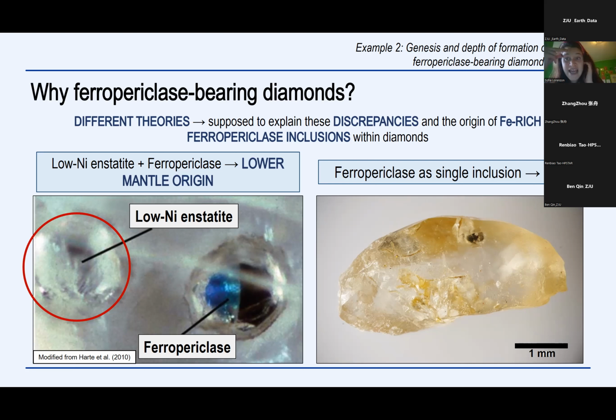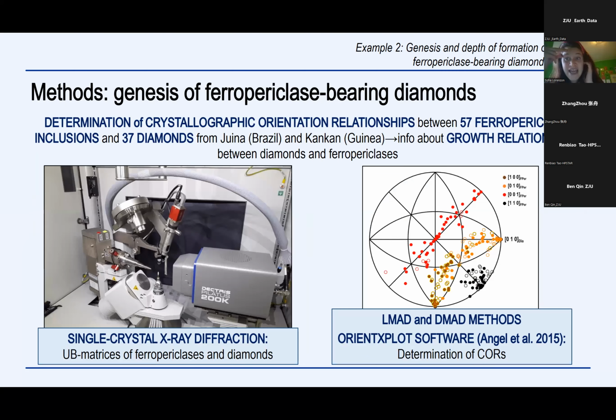But if ferropericlase is present as a single inclusion within diamonds, considering that ferropericlase can be stable also at depths shallower than the lower mantle, we are not able to determine at which depth this diamond formed and through which genetic processes in the Earth's mantle. So, to try to understand this, in this study we tried to determine the possible growth relationships that can exist between ferropericlases and diamonds in order to understand the possible genetic processes, determining, as I explained before, the crystallographic orientation relationships between these two mineral phases.